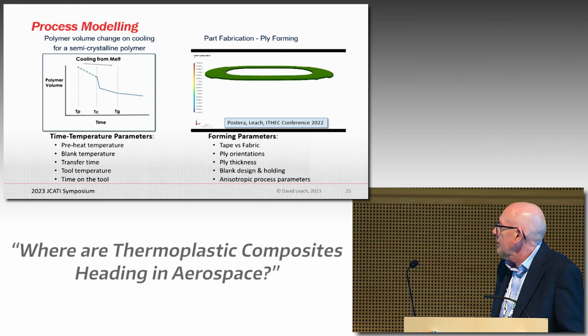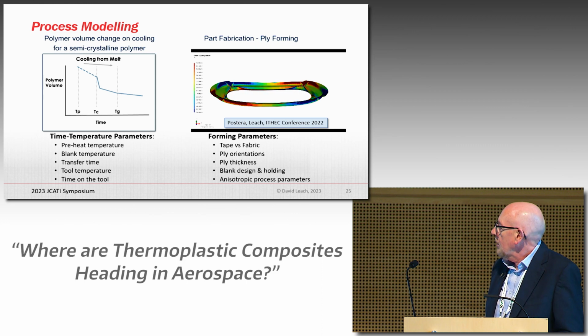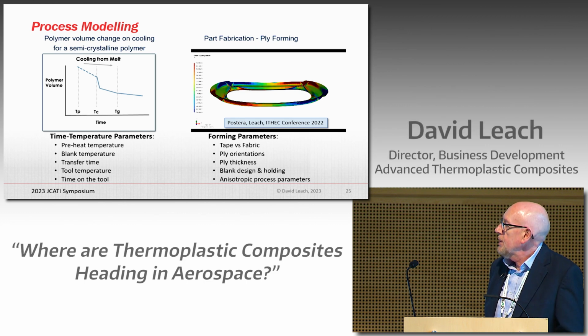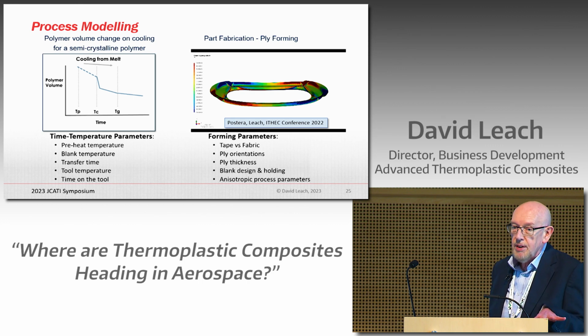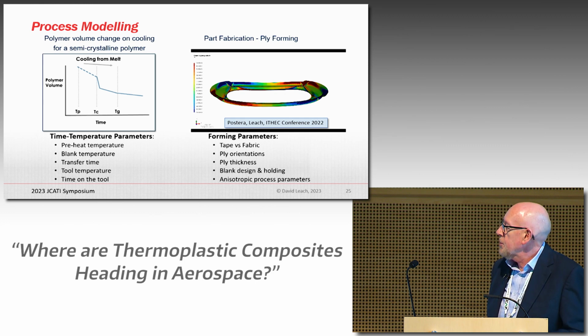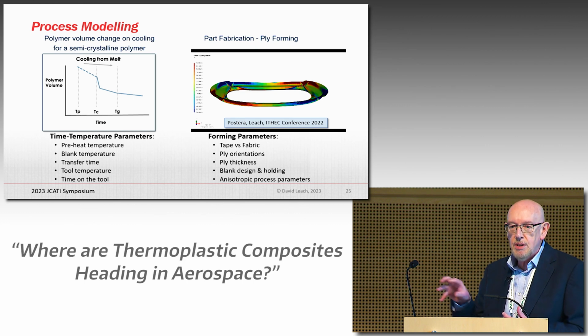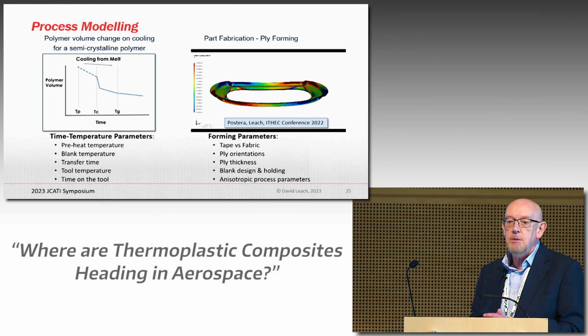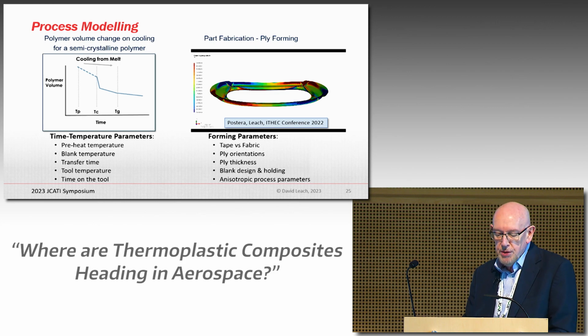We've kind of touched on process conditions a little bit, and how we control that, because of course we're starting off at quite a high temperature, in excess of 700 Fahrenheit. Cooling down, the polymers become more and more viscous. You hit a crystallization point, which is solidification, stress-free temperature. You also see quite a large volume change, of course, at that point as the material crystallizes. And then a couple of regions of temperature performance as well as you cool down through the TG. So modeling that and particularly relating that to the fabrication process is really important. And then the ply orientations, as we've seen in the illustration here on the right. So developing modeling software tools that are really specific to thermoplastic composite forming, which really draws a bit on isotropic materials like metal forming that's been done historically, combining that with some of the composite forming approaches.